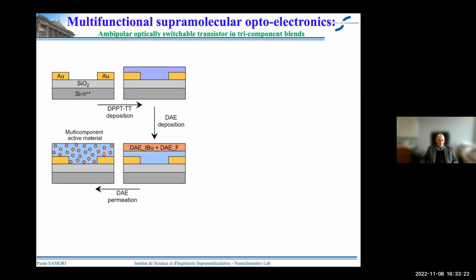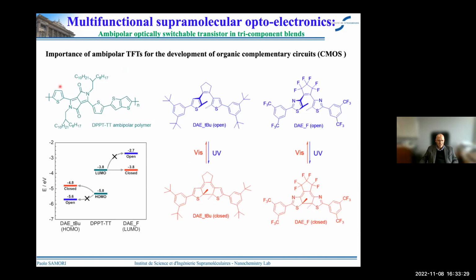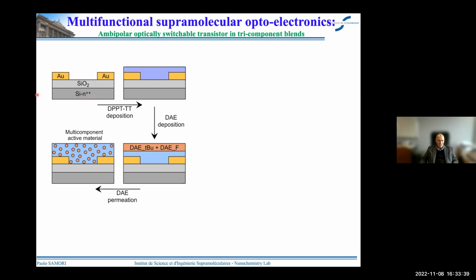Now, how have we fabricated our device? There is a peculiarity that I have to stress: this kind of polymeric semiconductor, to be ambipolar, needed to be treated at 300 degrees, and that is a temperature to which we cannot expose the diarylethene. So what we have done is we took a bottom gate, bottom contact, let's say, chip for a transistor. We deposit the polymer. We heat it up at 300 degrees.